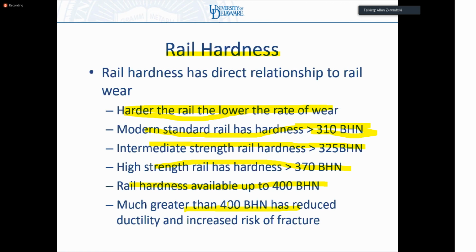For all practical purposes, we don't want rail harder than 400 BHN, because if you make a rail too hard, it's less ductile. It means it doesn't stretch as much, and that means it's more fracture prone. So if there's a small crack, that crack can propagate very rapidly. So because of the ductility requirement, rail is nowadays primarily between 300 and 400 BHN hardness.